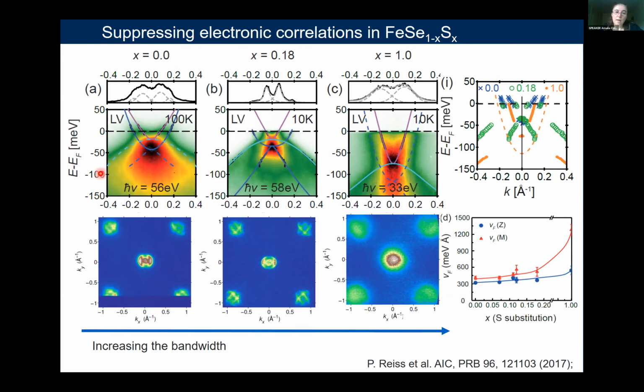Furthermore, in these systems, the correlations also change with sulfur substitution. So these are electron band dispersions for iron selenium in the tetragonal phase, and also for the 18% compound in the tetragonal phase, compared with iron sulfur, which is the right end member of these compounds. And we can see how the bandwidth increases, and also the velocities associated with the hole and electron bands significantly increase. That means the system becomes more metallic and less correlated as we go towards the sulfur end.